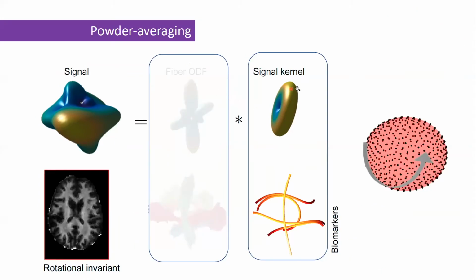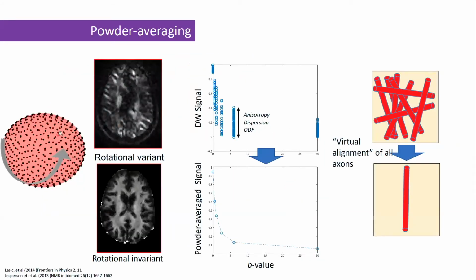Estimating simultaneously the ODF and the signal kernel is a highly complex optimization landscape. So it would be much easier if we can cancel out the ODF, so that we can decompose the problem and focus on the signal kernel itself. And that's actually made possible by something which is called powder averaging. Our diffusion weighted signal is acquired along many, many directions. Simply averaging the signals per B value over all those gradient directions cancels out that orientation distribution function. The top image here is just a diffusion weighted image at particular gradient directions. The bottom image is